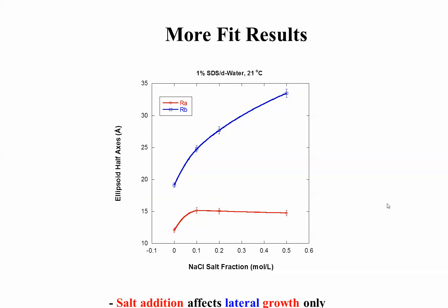More fit results. Here we added some salt. We found that ellipsoidal particles have a minor radius and a major radius. We found that the minor radius doesn't change much, but the major radius does. These ellipsoids are not like a football, but like a pancake. And when we add salt, it's just like the pancake is getting wider, but the thickness is not changing much.